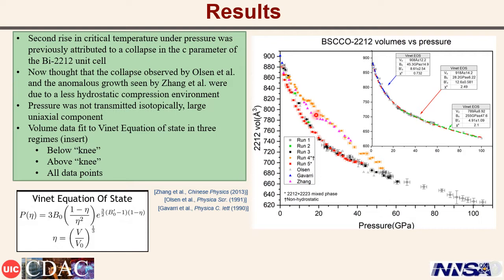We now believe these anomalies are non-hydrostatic effects due to the methanol-ethanol mixture freezing and giving a preferential compression direction. Our samples were in a neon environment, which is known to be much more hydrostatic. Data was fit to a Vinet equation of state, but a single equation did not adequately explain the entire curve.